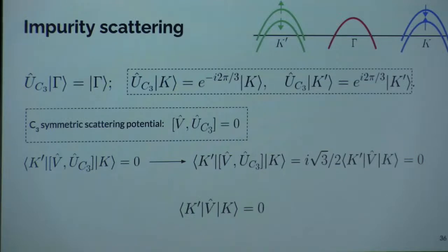Then, if it's C3 symmetric, V commutes with C3 rotation. In the first line, we see how the C3 rotation acts on each of the orbitals. So you see that C3 accumulates a minus i 2π over 3 phase for K. It's in the other direction for K prime. So if the commutator is 0, then we can form this expectation value, which of course also must be 0. Then we act with the C3 rotation operator on the states using the properties above. And then we immediately come to the conclusion that this scattering element, K prime V K, is equal to 0. Putting this mathematics into words, there is no scattering between K prime and K.